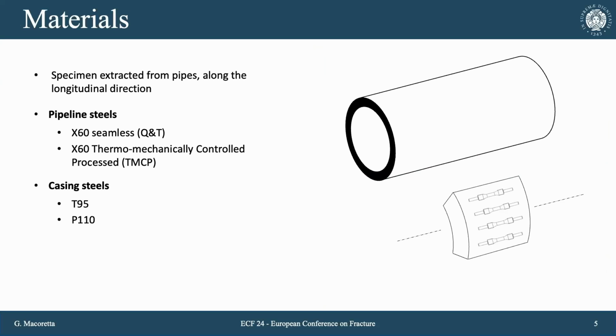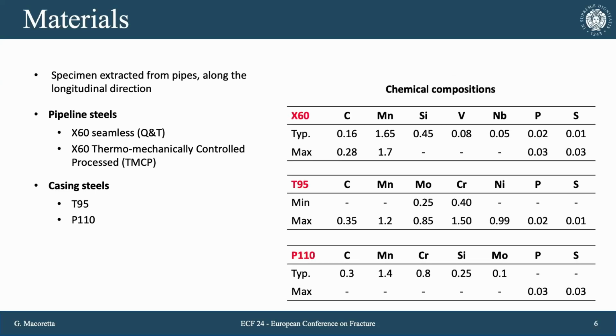Materials: we deal with X60 pipeline steel in the seamless configuration, so pipes produced via a seamless process, and thermomechanically controlled processed materials, so a material produced by bending and welding sheet steel, and casing steels T95 and P110. All the specimens were extracted from the pipe along the longitudinal direction, with the specimen axis aligned with the pipeline longitudinal direction. About the chemical composition, we are dealing with low carbon steels, in particular the X60, but in all cases we have a carbon content lower than 0.3, more or less.